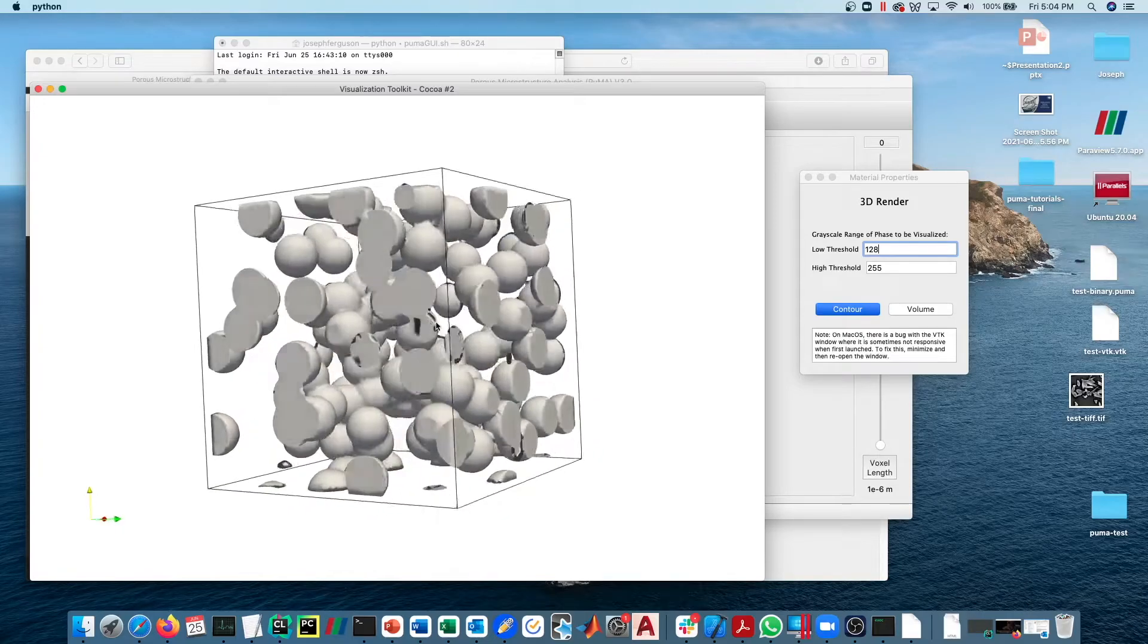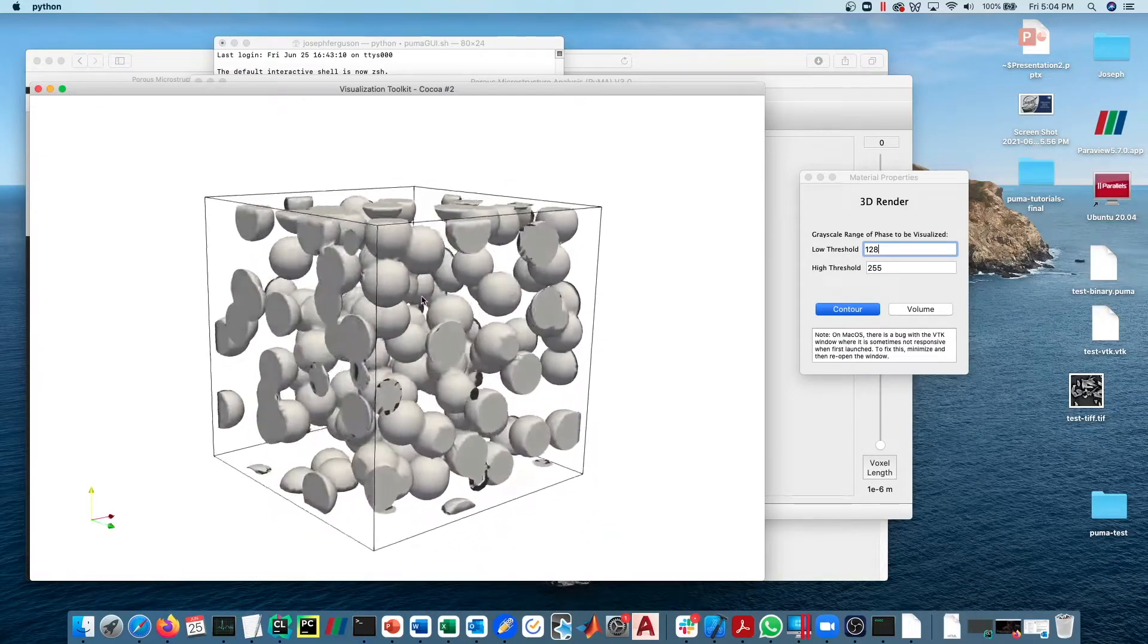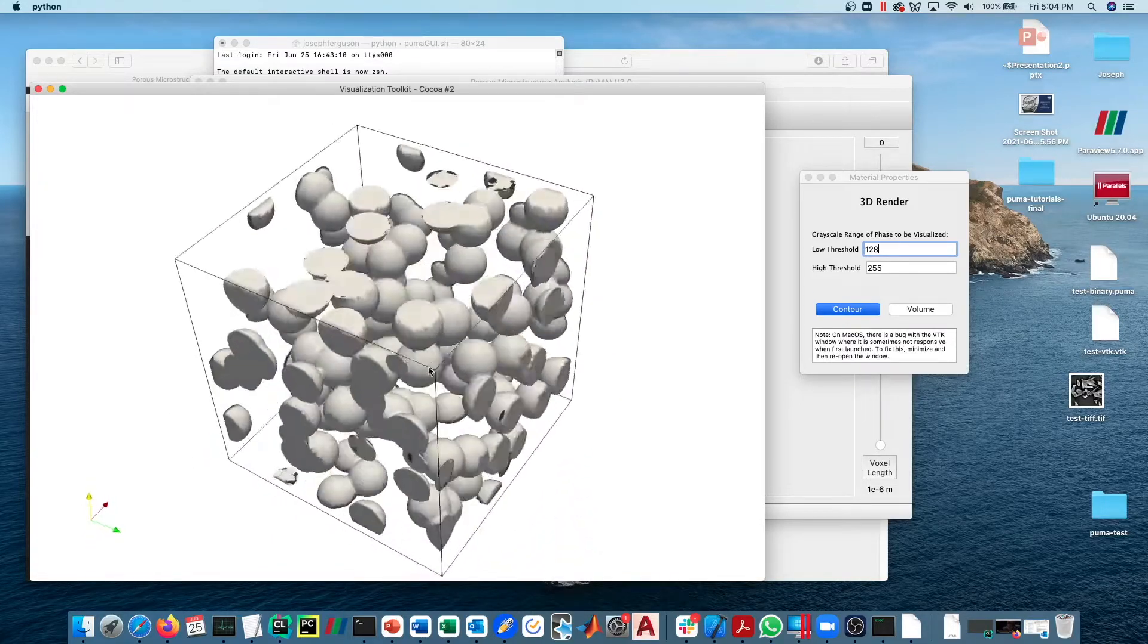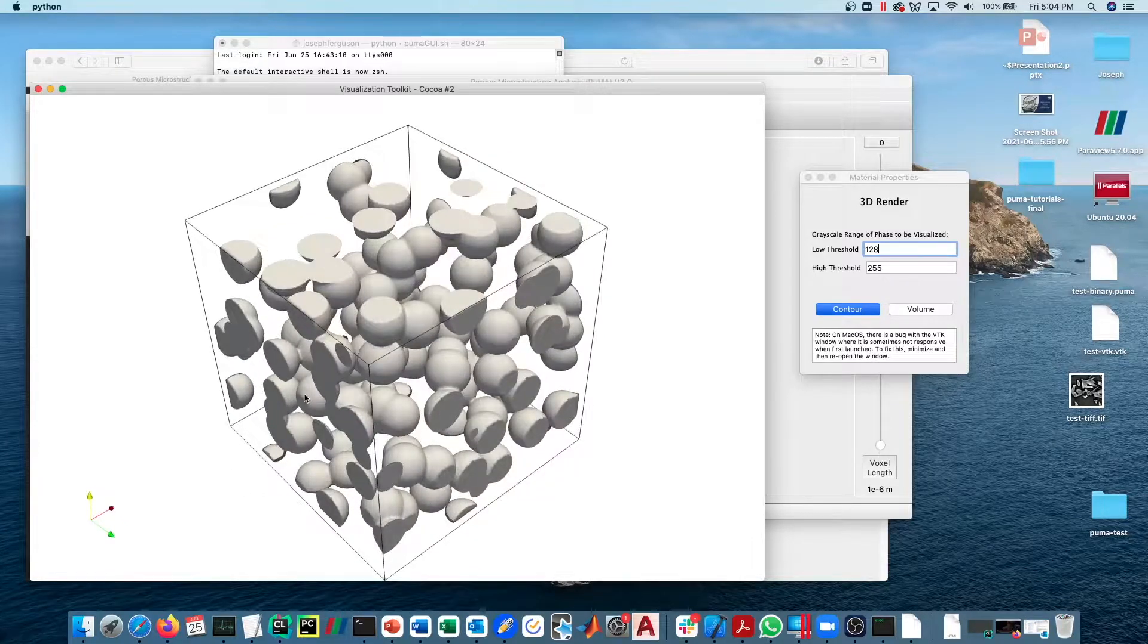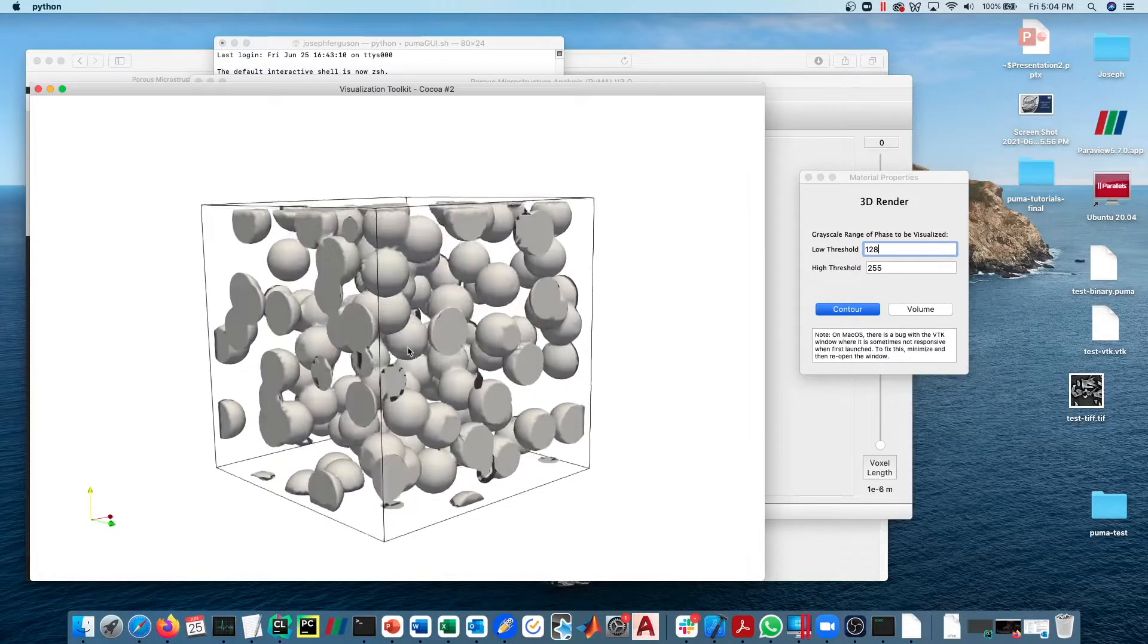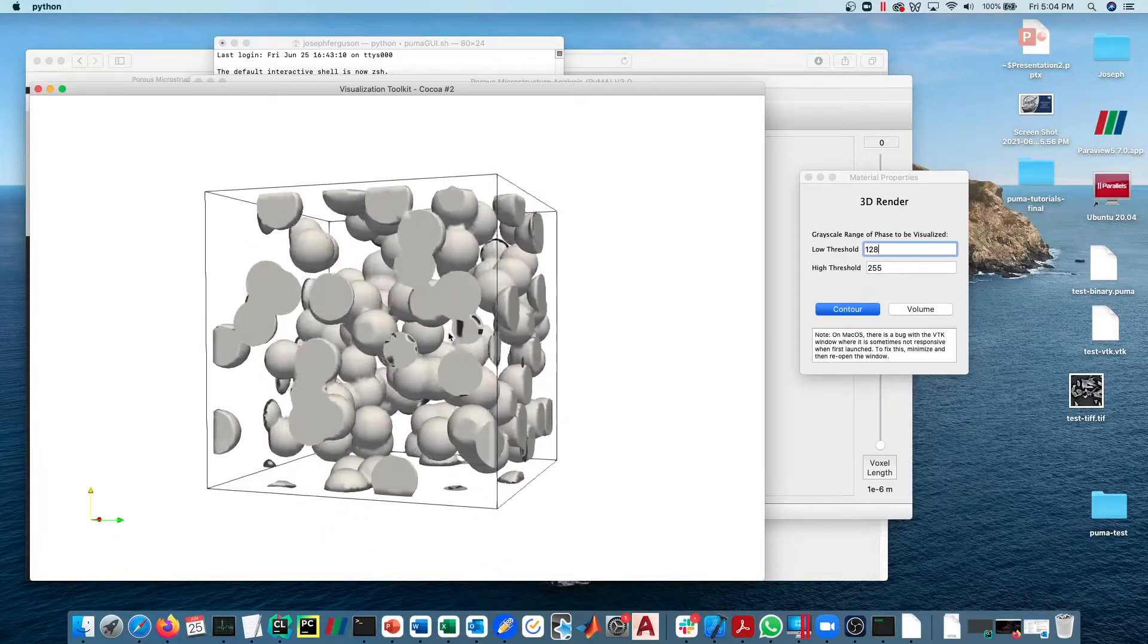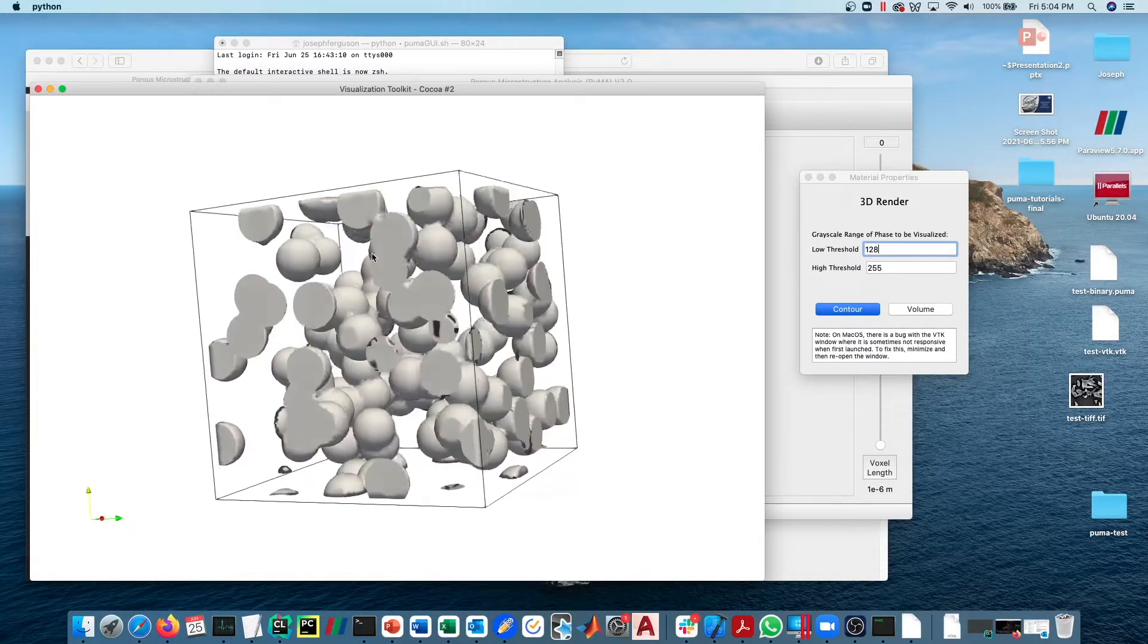Now the tortuosity, as I mentioned before, is a material's resistance to diffusion. As you can see with a material like this that is quite porous, it's unlikely that it has a very high tortuosity value. A tortuosity of one would be no resistance whatsoever. A tortuosity value of two would essentially be a 50% impediment on the diffusion. We would expect this material to maybe have a tortuosity of 1.15 or 1.2 or something like that.